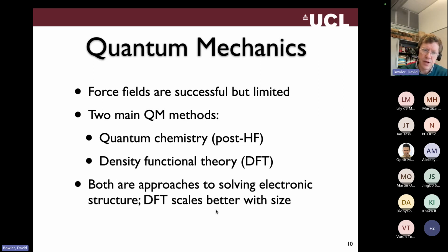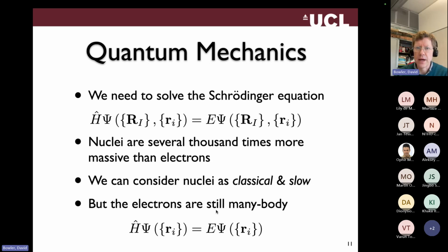It's a little bit of a generalization, but it's largely true. Typically, standard DFT methods scale with the cube of the system size. So you double the system size, it becomes 8 times slower or 8 times longer to run. Quantum chemistry starts around about the 4th power. So again, you double the system size, it takes you 16 times as long.